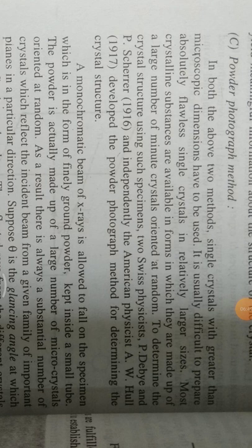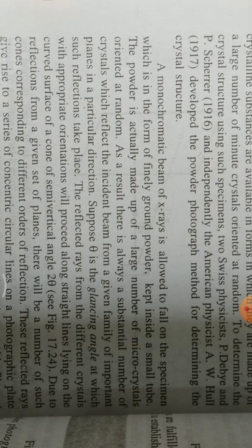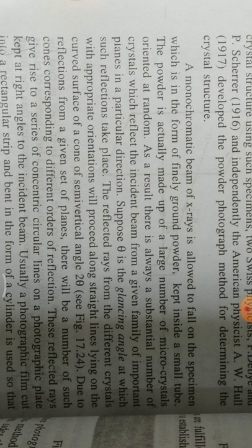Next, I talk about P. Debye and P. Scherrer, 1916, and independently the American physicist A.W. Hull, 1917, who developed the powder photographic method for determining the crystal structure. A monochromatic beam of X-rays is allowed to fall on the specimen, which is in the form of finely ground powder, kept inside a small tube. The powder is actually made up of a large number of microcrystals oriented at random.